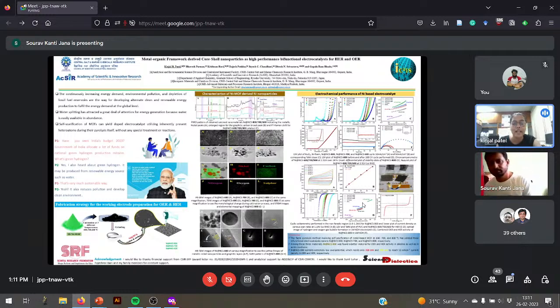The highest ID by IG ratio is obtained for the 800 degree calcined catalyst, which indicates the highest number of defects and disorder in the graphitic carbon, and which is also responsible for the conductivity and the ion transport activities. The morphological features have been characterized using scanning electron microscopy and transmission electron microscopy.